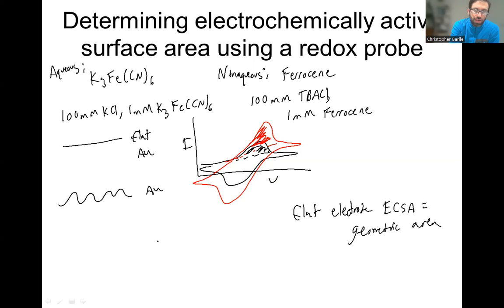Then you're going to say, whatever my flat area electrode is, I know that my bumpy area electrode electrochemical area is just equal to this charge that I integrate under here, the area under this curve. Assuming these are under the same scan rates, you don't even have to actually calculate the charge by dividing by scan rate. You can just look at the relative areas.